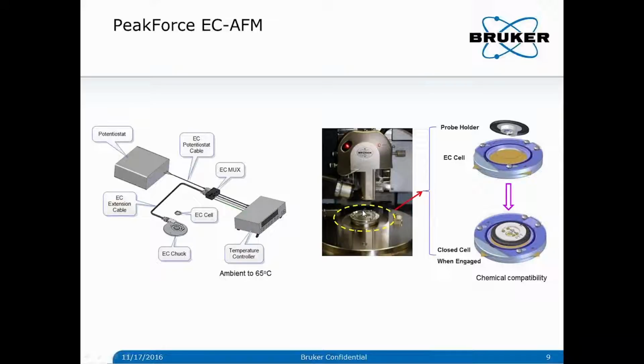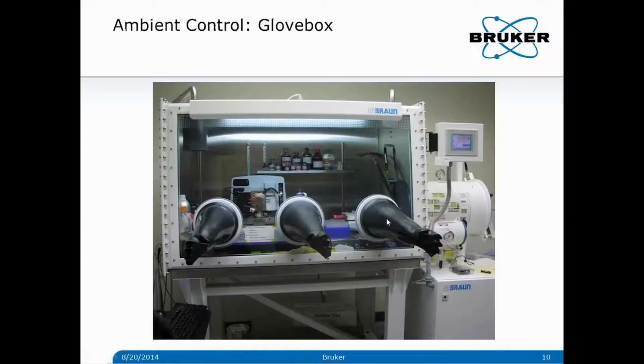And the EC cell, as you can see here, Ravi is going to give you more detail on that. The EC cell is designed to be compatible with a wide range of electrochemistry. Another important feature is that during imaging, the cell closes up upon the tip engagement. This is very important, especially for lithium-ion battery study, to avoid the evaporation and loss of volatile solutions. Since the samples, for example the silicon anode or the battery solution, are very sensitive to air and water, it naturally requires ambient control.